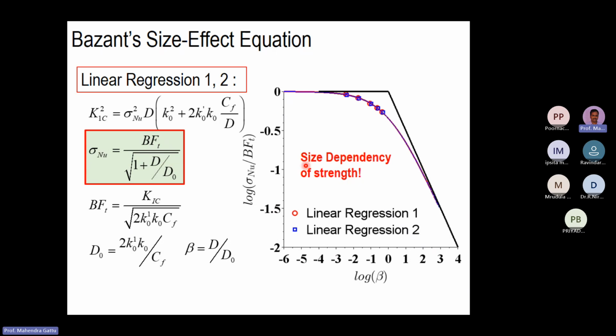What we have studied in mechanics of materials is that we calculate our sigma peak value for a given size in the laboratory, and then we use that peak stress value for design of actual real life structures. But from the theory of quasi-brittle fracture mechanics, we see that for larger size structures, the strength is less compared to a smaller size structure in the presence of cracks. In the presence of cracks, there is a size dependency of strength.